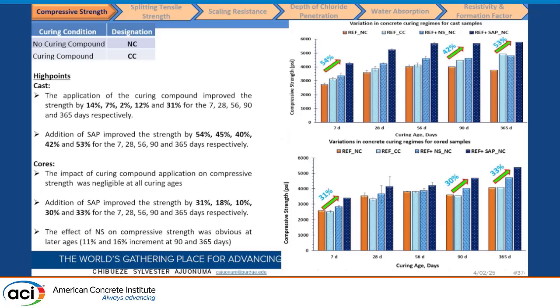And this is also a very interesting plot. We try to compare the effects of different curing conditions. The first bar is the non-curing, the slabs without a curing compound. The second bar is where we applied the curing compound to the slab, and then with the addition of nanosilica, and then with the addition of SAP. And we noticed a gradual increase across all ages, 7 days, 56 days, 90 days. We noticed an increase with the addition of SAP, showing the internal curing performance of SAP in concrete.